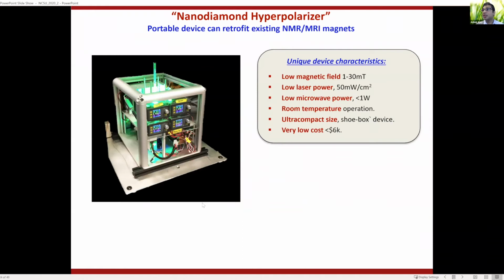So in any case, it turns out that because you do it at room temperature, low field, etc., it's very easy to generate polarization. And light also is very special. There are many ways by which you can deliver light to a system. So in any case, we built this small polarizer device. This is about the size of a shoebox, and you can put nanodiamonds into it, press a button, and polarize these nanodiamonds very highly. But the important thing is the very benign conditions in which it operates. Very low magnetic field. It's the magnetic field of a refrigerator magnet. Very low laser power. So it's a small laser diode or LED, basically. Very low microwave power. So just a Wi-Fi microwave amplifier, works at room temperature. It's a very small device.